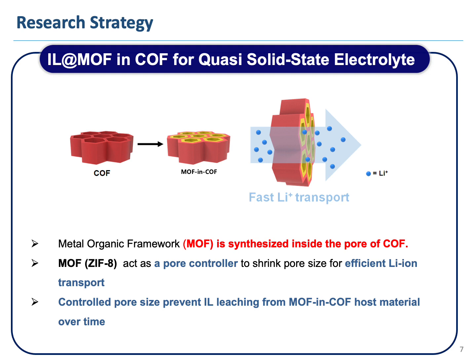Here, we chose metal organic framework, MOF, which is a crystalline material composed of a metal ion linked by organic ligands with ultra microporous structure as the materials for hybridization with COF to control the pore size. We propose an IL at MOF in COF for quasi solid state electrolyte.